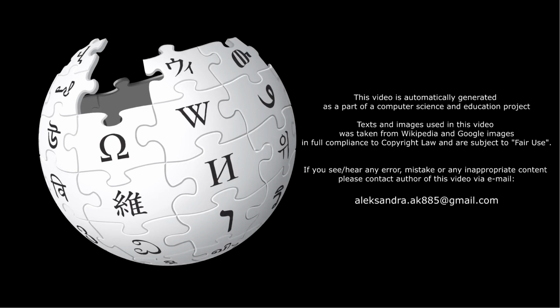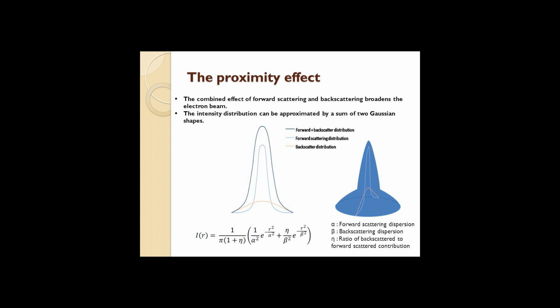but the generation of secondary electrons is inevitable. It is now recognized that for insulating materials like PMMA, low-energy electrons can travel quite a far distance. Several nanometers is possible. This is due to the fact that below the ionization potential, the only energy loss mechanism is mainly through phonons and polarons. Although the latter is basically an ionic lattice effect, polaron hopping could extend as far as 20 nanometers.